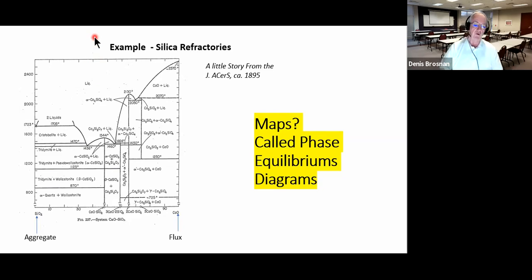So he mixed it up, went out to the mixer, poured it in. Well, of course, at night, the family members snuck into the office and found out the white powder was lime. It was a flux. So it's this system right here. You add the right amount of lime to silica, we're going to form liquid, and we're going to make a quality ceramic. Well, unfortunately, the family was not honest, and they discharged the British engineer. I guess he went back to Britain, and perhaps that says a lot about ceramic history or about American industry during that time period.